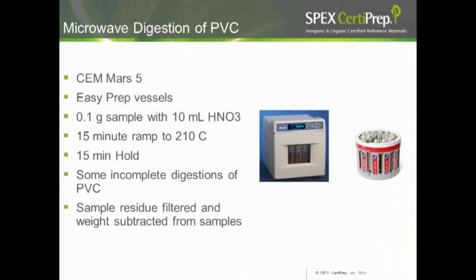And this could be because there are certain additives that prohibited the complete digestion, or maybe the additives themselves didn't really digest. We should have maybe brought the temperature up in order to digest that additive. But not knowing what some of these potential plasticizer additives were, we did have some incomplete digestions. And we handled that in a very normal way, by taking our sample residue, filtering it and then drying it.